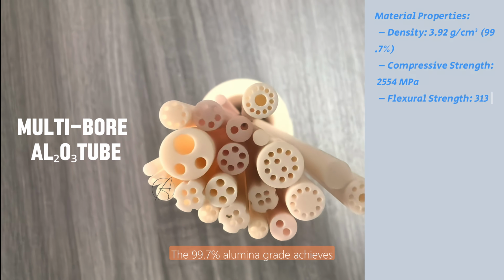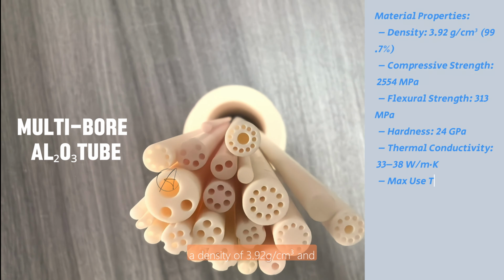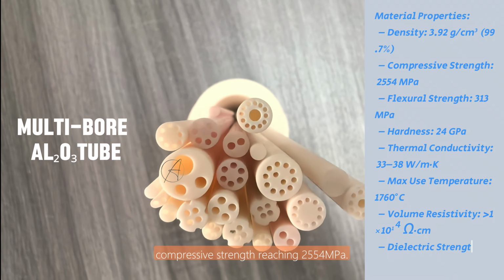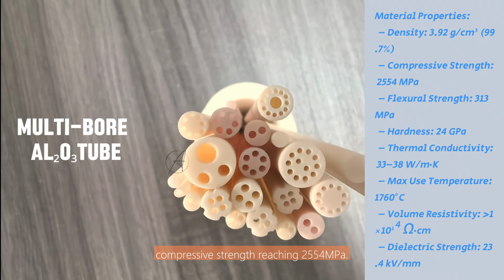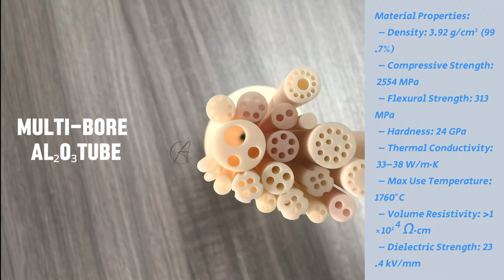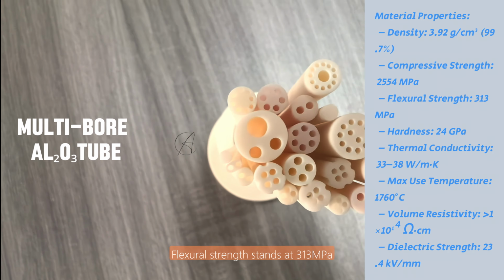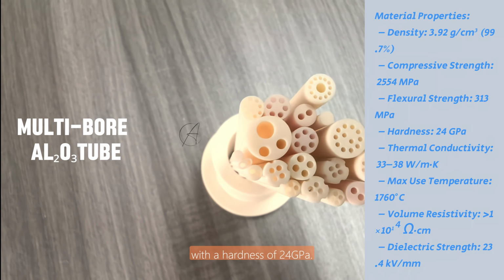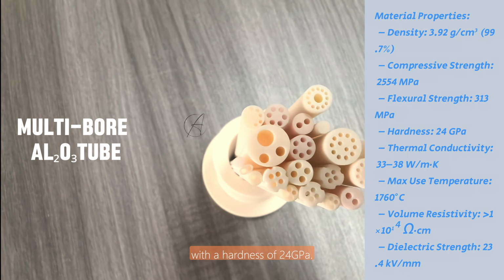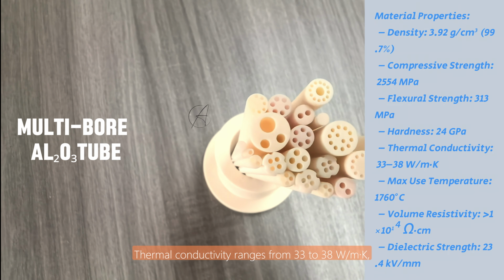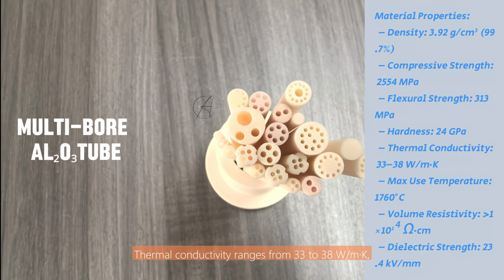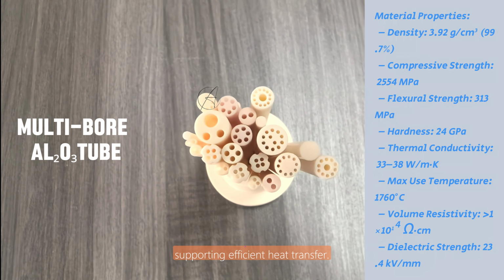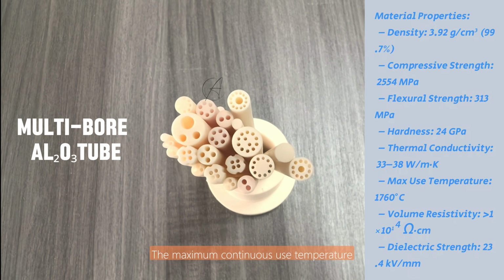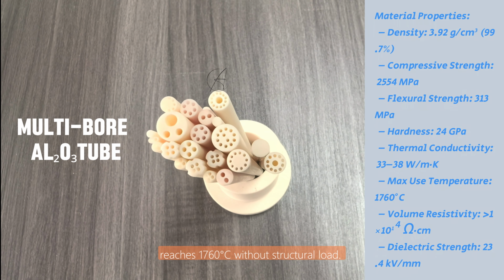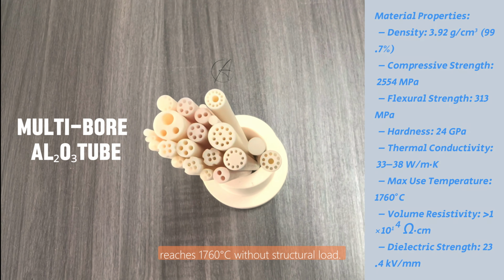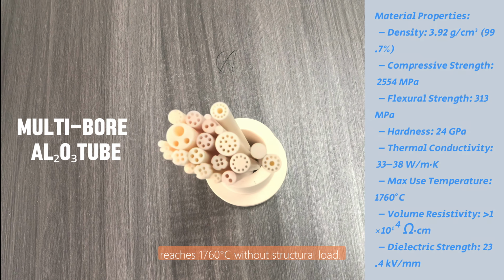The 99.7% alumina grade achieves a density of 3.92 grams per cubic centimeter and compressive strength reaching 2,554 megapascals. Flexural strength stands at 313 megapascals with a hardness of 24 gigapascals. Thermal conductivity ranges from 33 to 38 watts per meter Kelvin, supporting efficient heat transfer. The maximum continuous use temperature reaches 1,760 degrees Celsius without structural load.